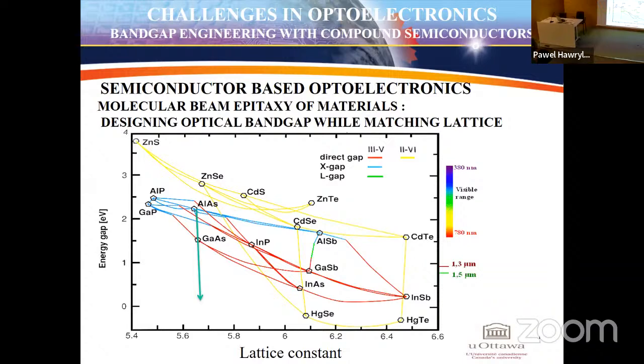So quantum Hall effect, fractional quantum Hall effect, quantum cascade lasers, and so on, are all based on this combination of materials, and now you see why, because the lattice is almost the same. So you can change the concentration of aluminum, but you don't generate any dislocations and defects. On the other hand, in the gap range of 1.3 to 1.5 micron, which is your minimum transmission for silica fiber, the telecom window, you have to go to the indium phosphide, indium arsenide system.